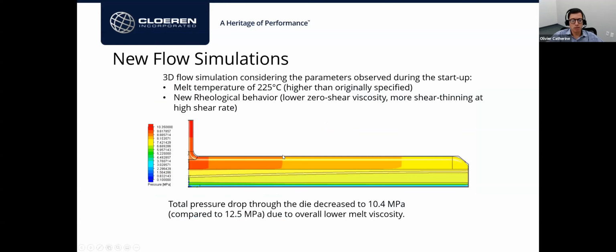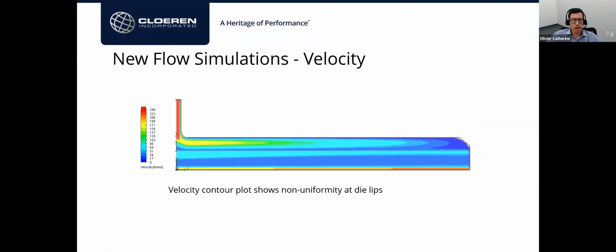So when I took into account all these changes, higher melt temperature and change in the viscosity behavior, well, first I found a lower melt pressure compared to the 12.5. We predicted 10.4 megapascal, so it's about a 20% reduction in the melt pressure. And regarding velocity, I can see also a trend, which is a much higher end flow.